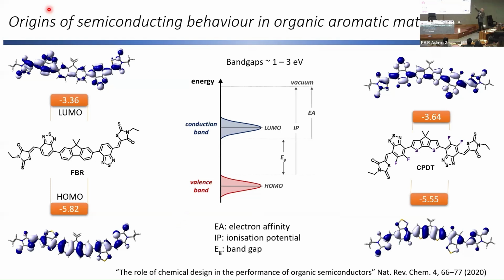At the same time, you see that the LUMO has actually dropped. And the reason that it's dropped is we've introduced electronegativity into the molecule, and that stabilizes the excited electrons that are in the conduction band. So by just substitution of a very small amount of atoms in this molecule, we can significantly tune its energy levels. And this is the basis of what we do as organic chemists in order to be able to design molecules for organic electronics in general.